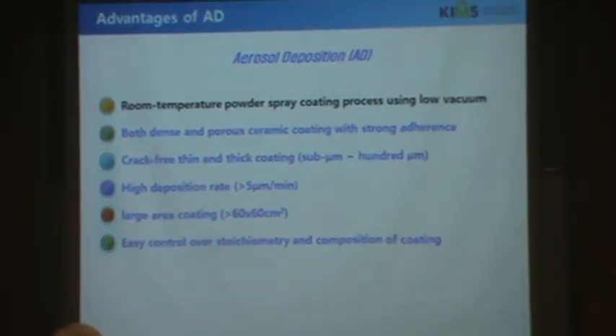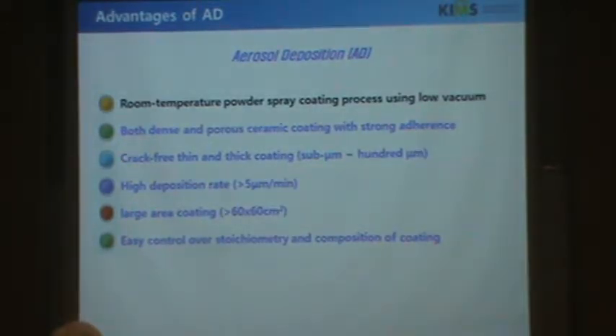And there are some advantages. You can make a very thick layer, like 100 micrometers, very fast. And we can make thin and thick coatings without cracks. And we can coat dense or porous substrates. We can control the stoichiometry because we don't have to change the powder. We can use the raw powder material. So we don't have to worry about the stoichiometry and composition of the coat.